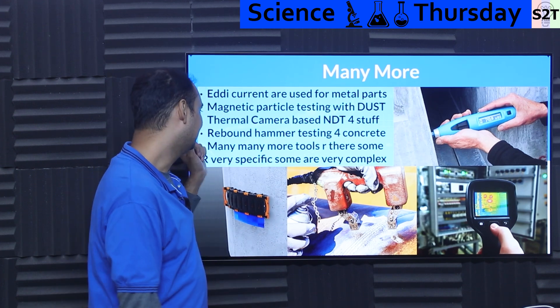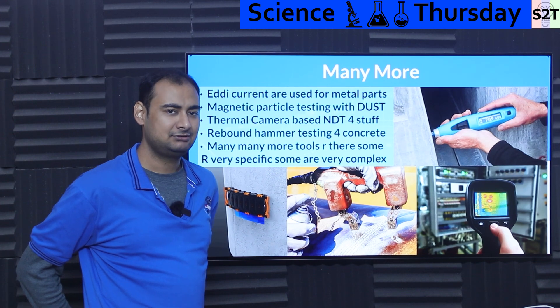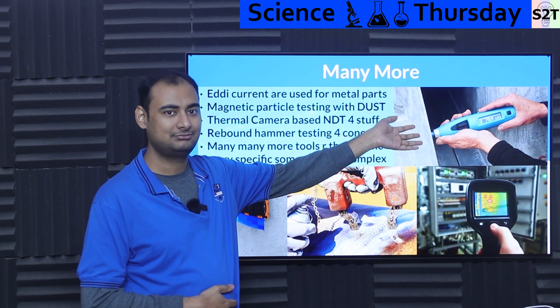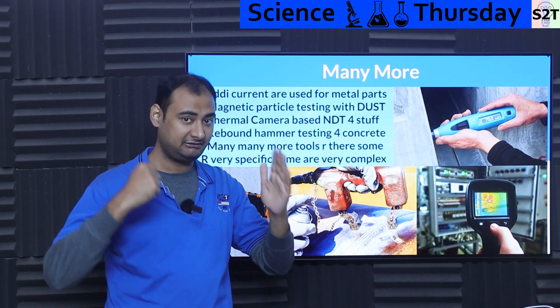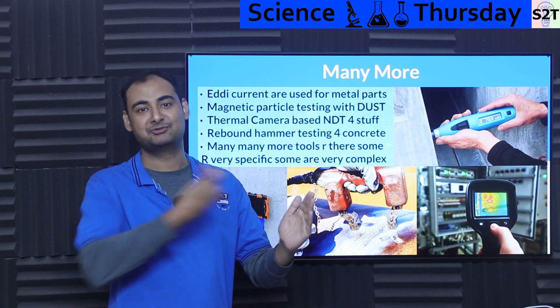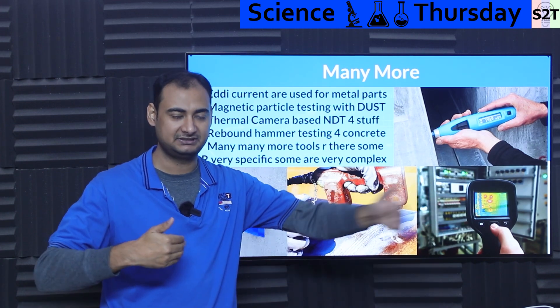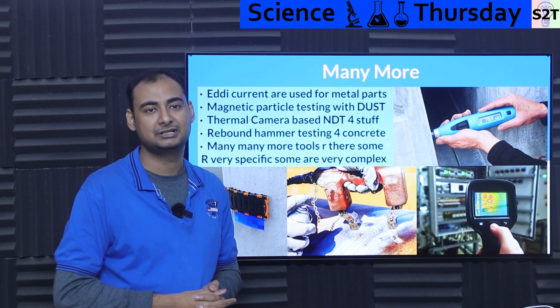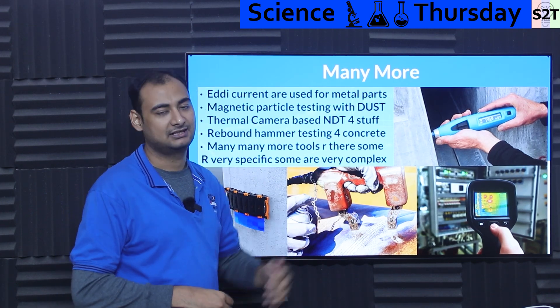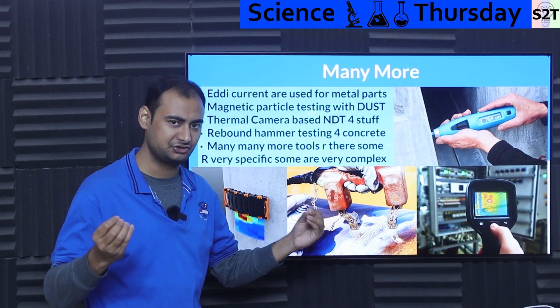My personal favorite is low-cost rebound hammer testing. Let's say you bought an apartment — how do you know that concrete pillar is actually a solid concrete pillar? You can buy this hammer, which has a very well-calibrated spring tension and mass. You press it against the surface and it bounces back. Based on the rebound, combined with a chart accounting for how thick the concrete pillar is, you get a number and you know how good the concrete is. It's a low-grade system, but more than good enough to tell you whether you need to evacuate or not. It also shows degradation — if rebar is corroding inside, it will start to show. A very useful tool that house inspectors can carry to validate concrete structures.